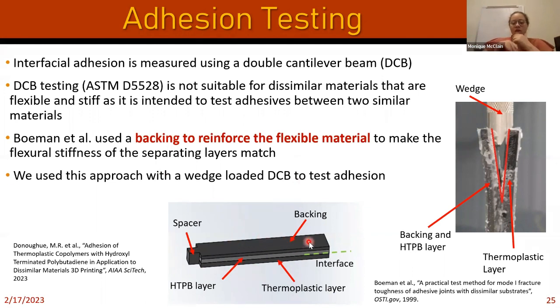So essentially, we can see that that thermoplastic backing is not as thick as the thermoplastic layer. The only reason it's there is to reinforce the HTPB so we can bend the two parts away from each other more equally. So in practice, it looks something like this. It's a bit messy because we have to improve our mold process.